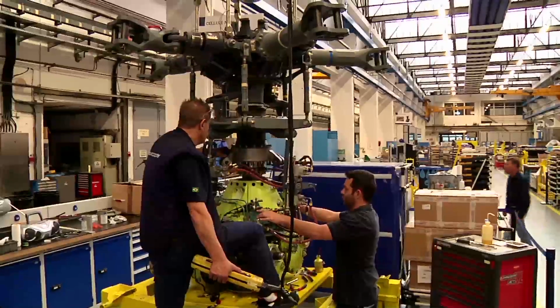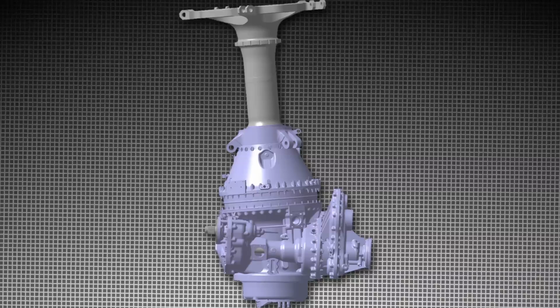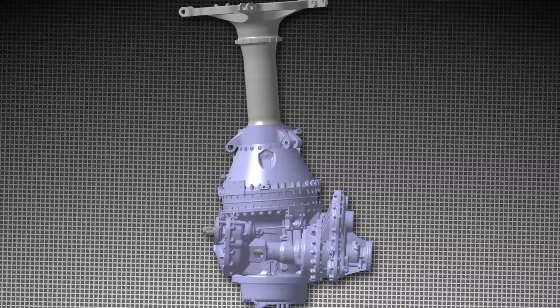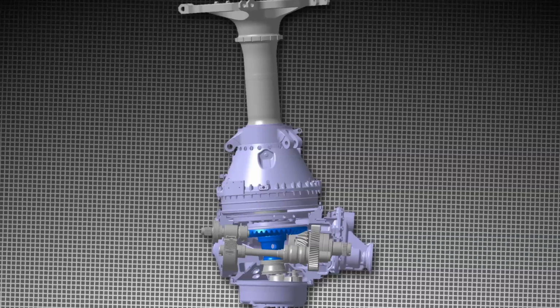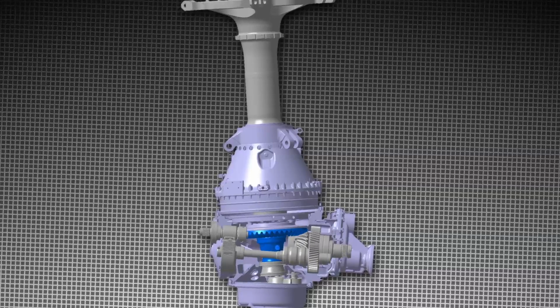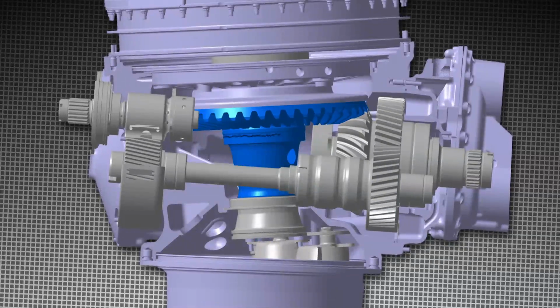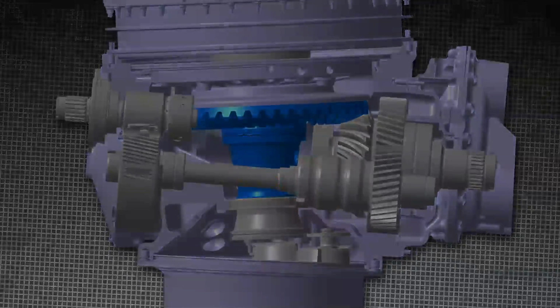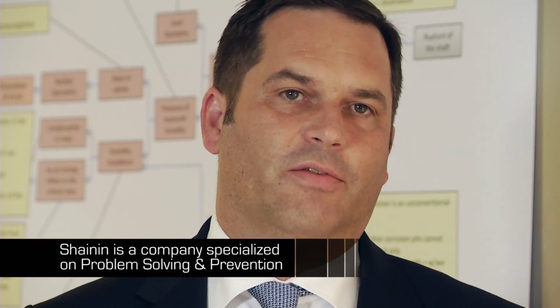Regarding the investigation on the EC225 main gearbox bevel gear vertical shaft, Eurocopter's opinion is that the crack initiation in the welded area resulted from the combination of three factors. All three factors must be present to initiate a crack. We are convinced that the Eurocopter findings in terms of the root cause analysis are correct, and we are in a process of closing out all the remaining failure tree branches.